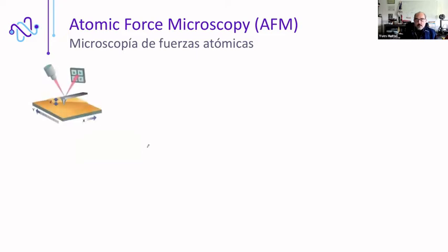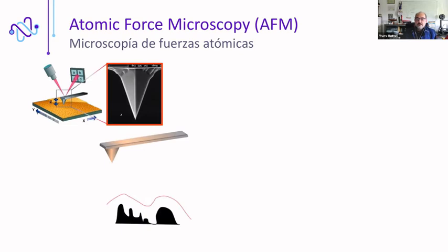The AFM resolution of the AFM images is extremely dependent on the sharpness of the tip you are using. You can understand that the tip is convoluted with the surface you want to measure. If you have a tip like this one, you will probably get this profile of this object, and you won't see the asperities of your object, of your surface.